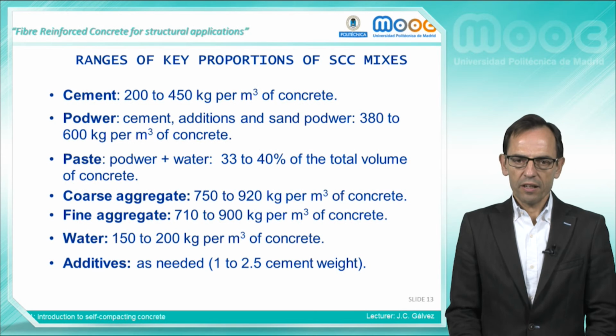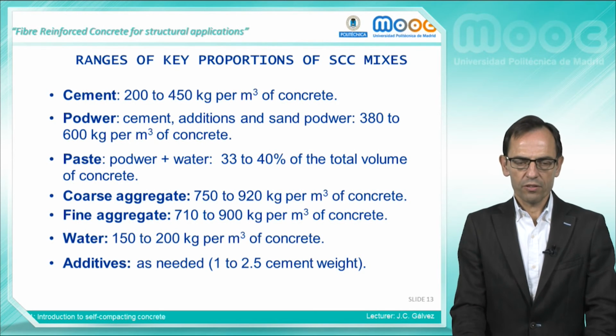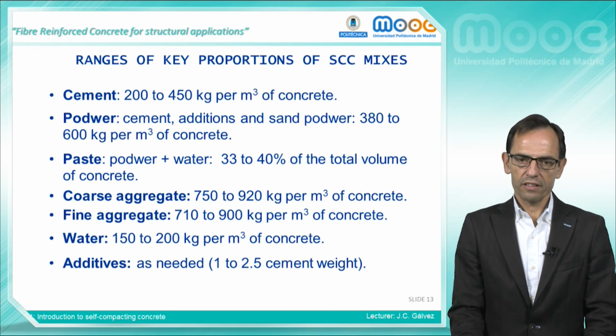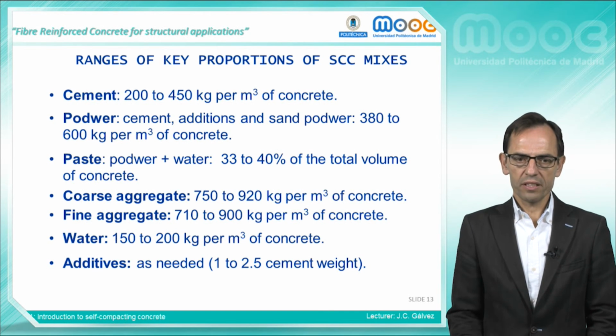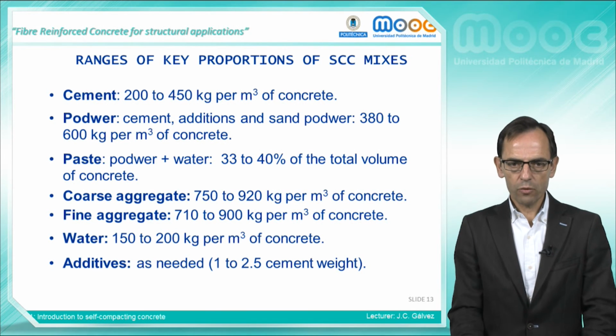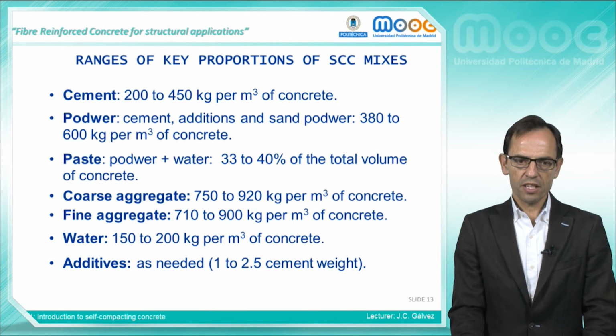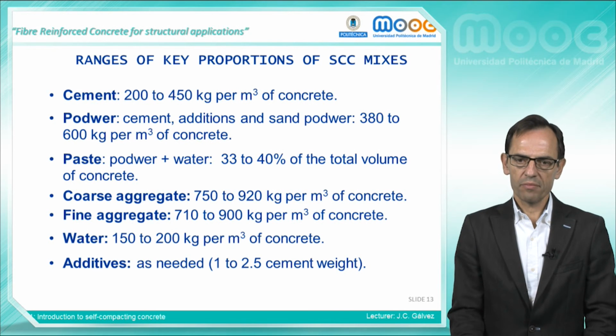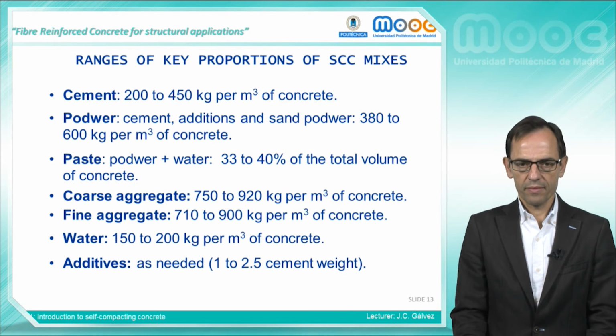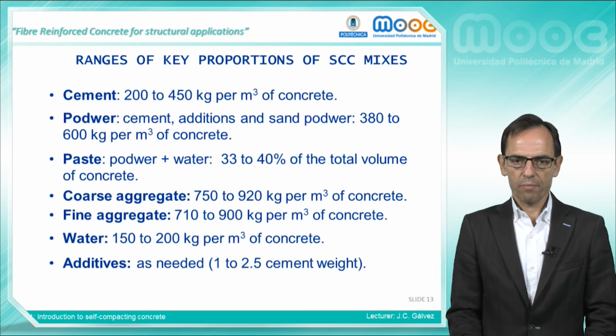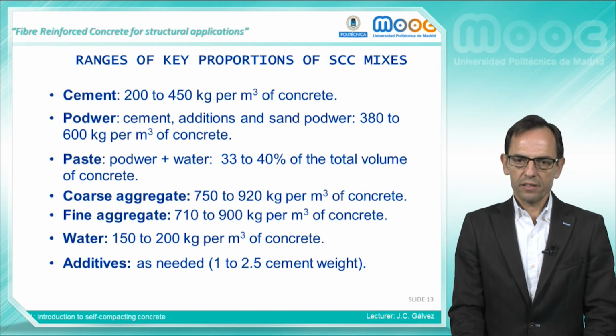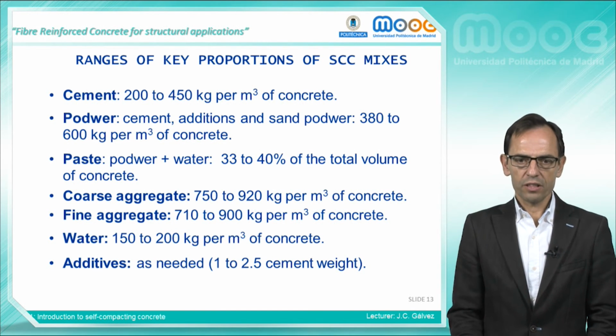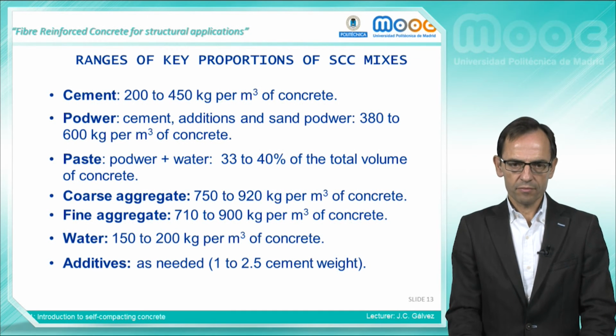Range of the key proportions of self-compacting concrete. Cement, 200 to 450 kg per cubic meter of concrete. Powder, that is cement, additions and sand powder, from 380 to 600 kg per cubic meter of concrete. Paste, powder plus water, 33 to 40% of the total volume of concrete.